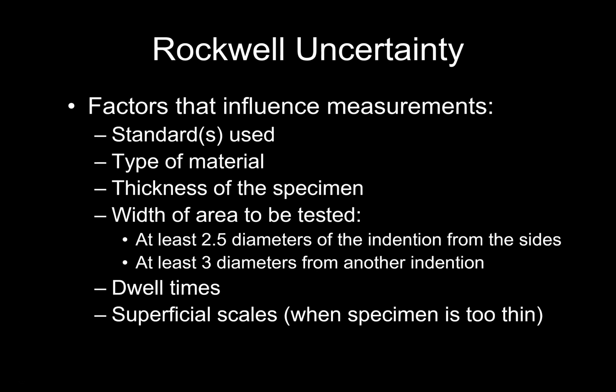The dwell times are important, and since we are performing Jominy experiments where the specimens are exposed at high temperature, you're going to see on the specimen an oxide forming, and so it's very important to remove this oxide or you will affect the depth of penetration of the specimen, which also could be a problem if your specimen is too thin, because you are removing a certain amount of material due to the oxidation.